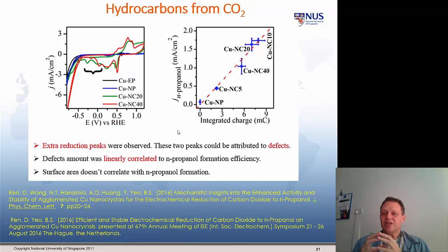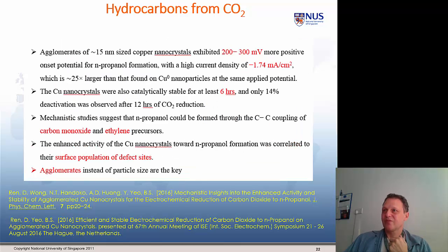Effectively, it's not straightforward: you've got a 2-carbon unit and a 1-carbon unit that have to react, and they have to be on the surface at high enough concentrations for long enough to react. And it's been shown that defects stabilize those intermediates and hence allow this work to happen. So I commend the paper to you.